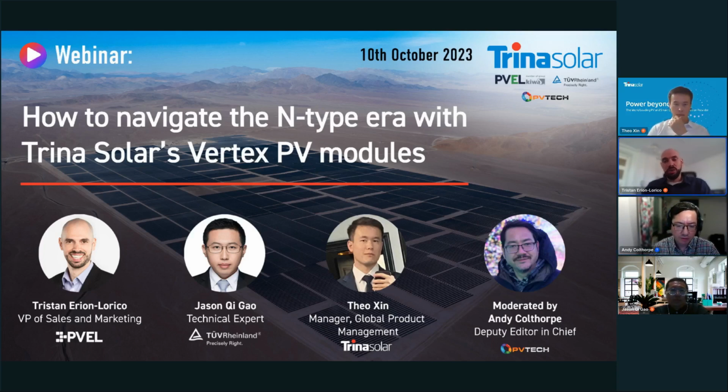Well, going back to the modules that were top performers for Trina in the 2023 scorecard, their N-type modules had less than 2% degradation following PID testing. But as I previously mentioned, we've seen other modules with higher levels of PID, and I would say, a concerning amount of PID. So, I wouldn't say that N-type modules, whether it's TOPCon or HJT, are intrinsically not susceptible to PID.